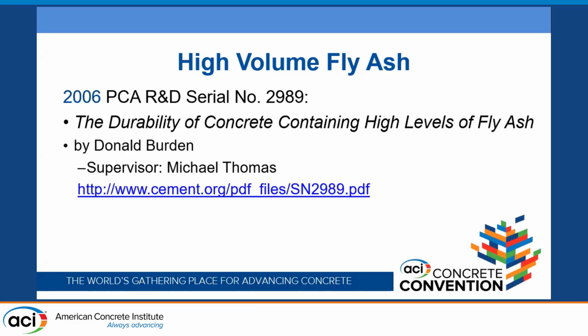And it showed that the degree of moist curing is important, and it needs to be offset by specifying lower water cementitious materials ratios, extending moist curing period, and also increasing the depth of cover when concrete is used. So all of these things are rules for corrosion resistance in concrete, and they can become staples for code requirements for reinforced concrete structures. So this is very important work that, as mentioned, SCMs are a wonderful thing, but using higher amounts isn't always going to get you what you need.